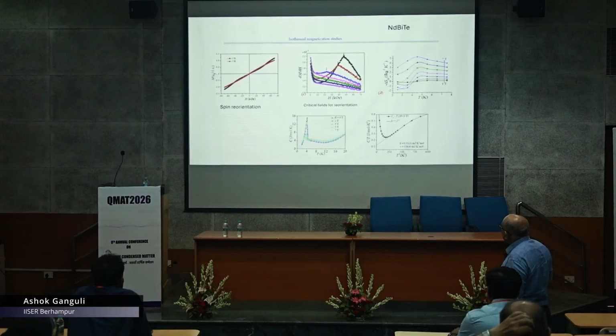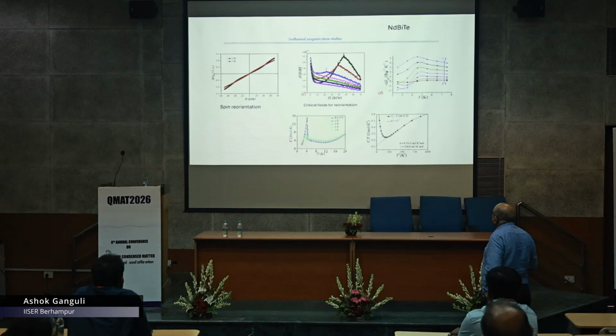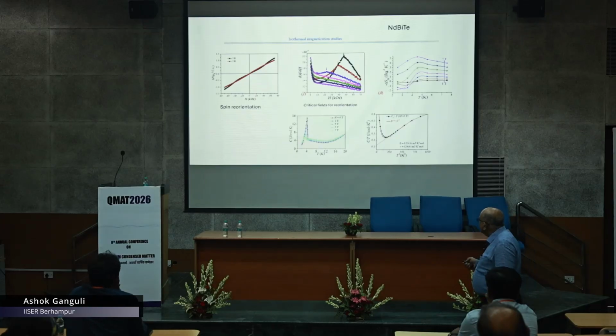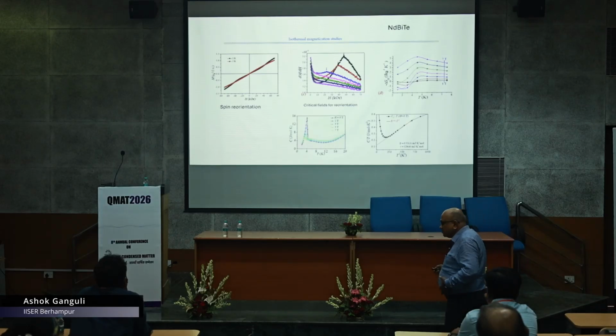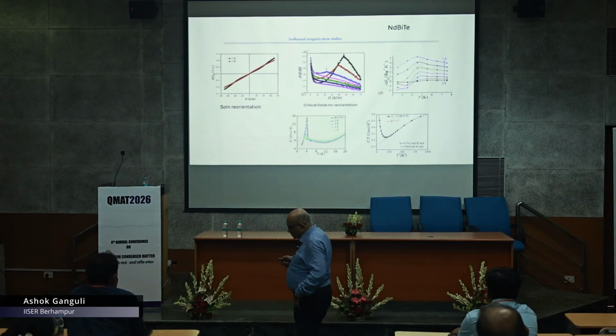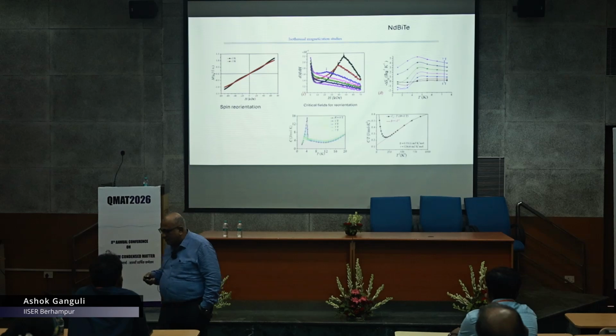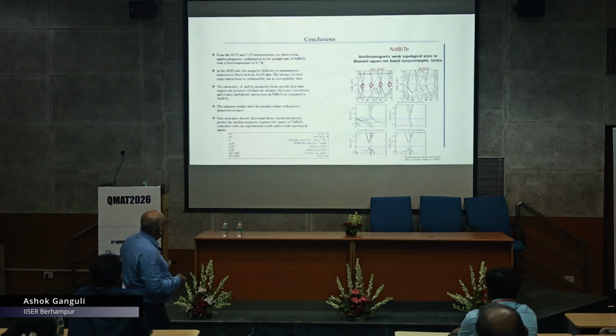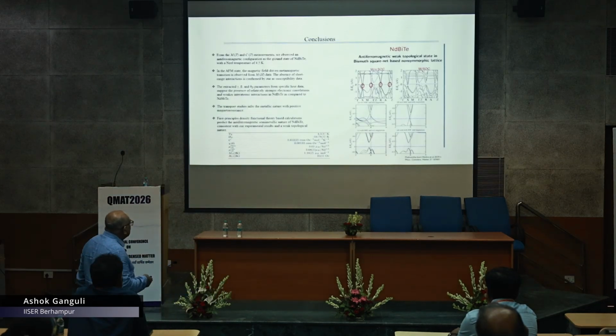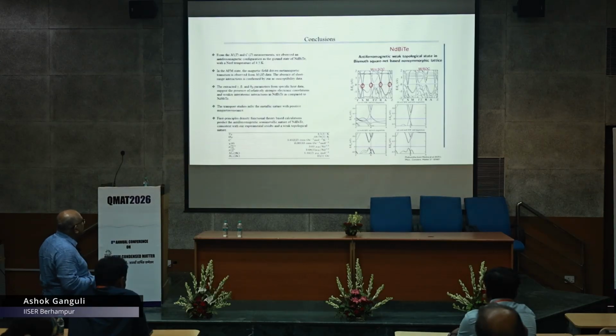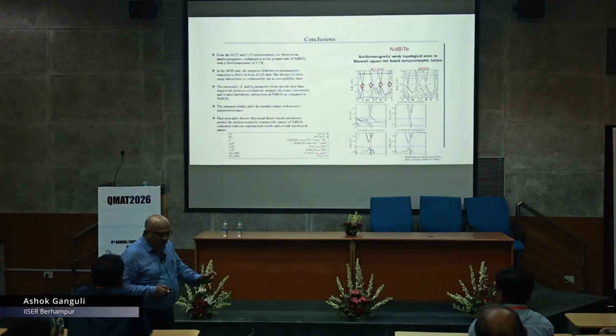So you can look at other properties, like the metamagnetic transitions, which vary as a function of field, and you can get these transitions. You can measure the specific heat and get the numbers, the beta, gamma, and theta values. So usually in many of these 111 type compounds, you see these metamagnetic and spin orientation transitions. So we did these calculations.